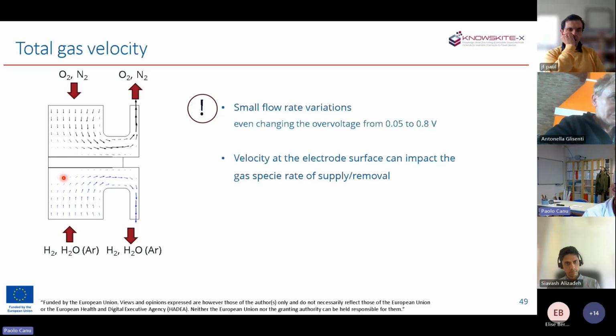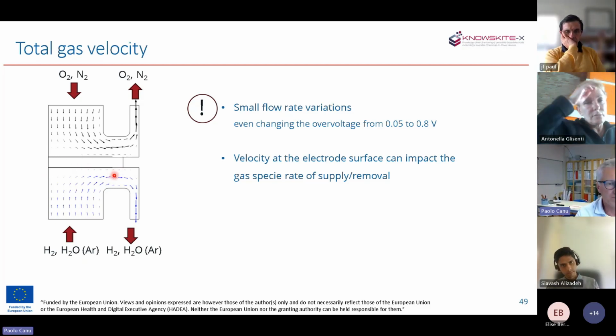So probably this configuration is called stagnation point, because you're feeding a gas against a wall, so the gas must diverge and flow from the periphery. It's leading to a stagnation region on both sides that is not useful to make sure that the oxygen or the hydrogen in front of the electrode is sufficiently uniform.